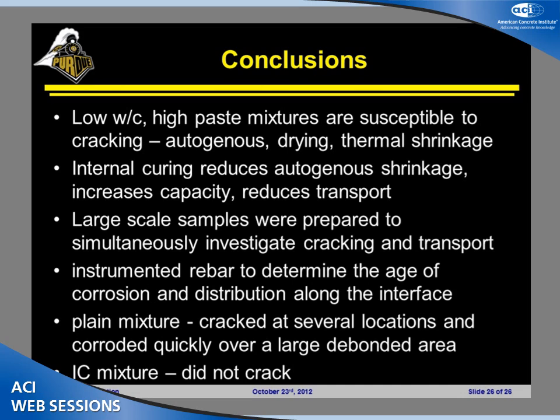Internal curing reduces the transport. We've begun a program looking here at these large-scale slabs to simultaneously investigate cracking and transport to bring those two things together. The instrumented rebar has helped us because it's not only determined the age at which corrosion is beginning or the fact that we're getting corrosion in the system, but we're also able to see things like the distribution along the interface, which can be substantially further back from the crack than originally thought. The plain mix, the takeaway here is it cracked at several locations, went into corrosion very quickly. The internally cured mix didn't crack and is still being monitored for corrosion. So with that, I'll turn it back over to Anton.